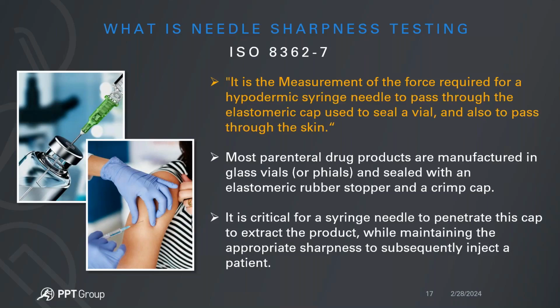And then after that, you move to a second part of the test where you penetrate the skin to make sure you get similar values as you did. In this case, the lower values would indicate that the needles are indeed meeting your sharpness standard, whatever those are, depending on the actual size. I've seen different sizes of needles, size and diameter of the needle.